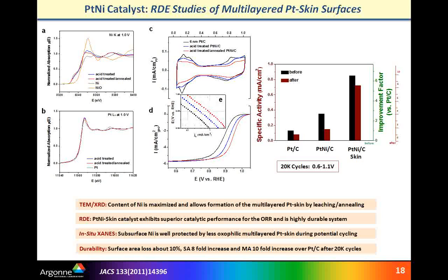of the same size and the same loading. But what is even more impressive is how that catalyst behaved after 20,000 cycles between 0.6 and 1.1 volts. And one can see that specific activity drop was really negligible. And the main reason for that is the fact that specific surface area did not change. In other words, we were looking into catalyst which was at the same time very active and very stable.